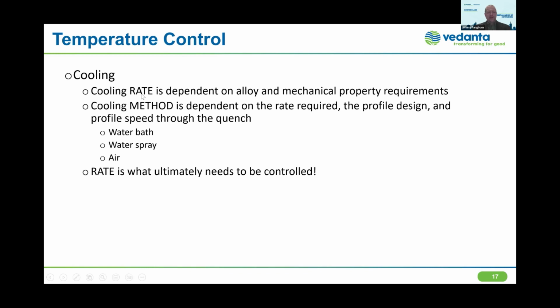The cooling rate that's required is going to be highly dependent on what alloy we're extruding, and there may be some variations depending on the mechanical property requirements. Most of what we extrude, if we're a facility that extrudes, for example, out of 6063, we may primarily just have one mechanical property requirement and not have a lot of variability there. Cooling method, there are different ways to apply the cooling. We saw water quench in the video that we showed. There's different types of water bath or water spray or air, but I do want to emphasize that the rate is ultimately what needs to be controlled, not the method. The method is the means to an end.